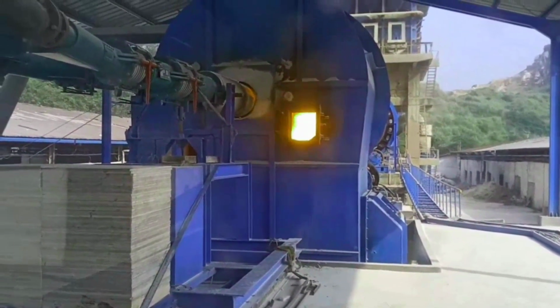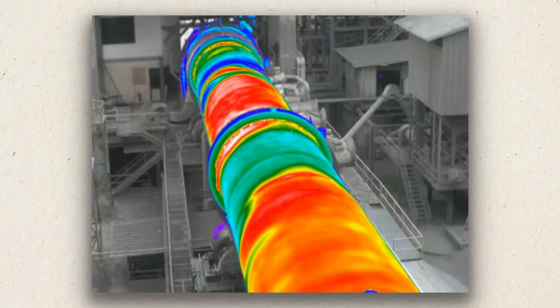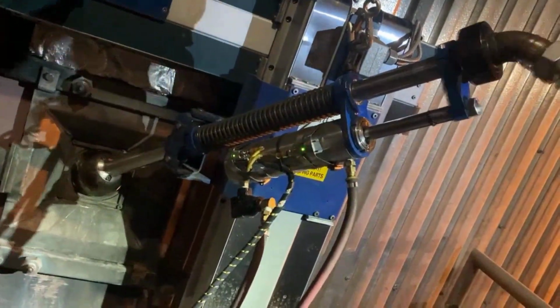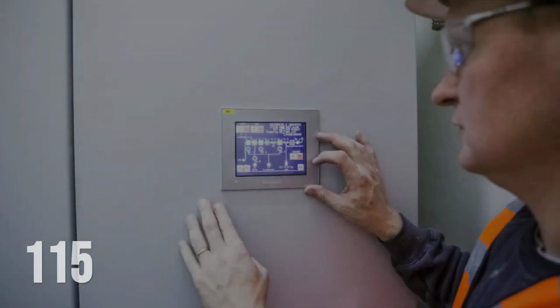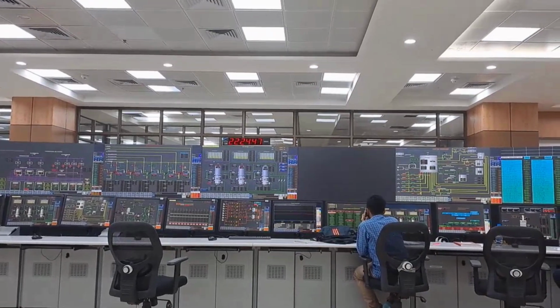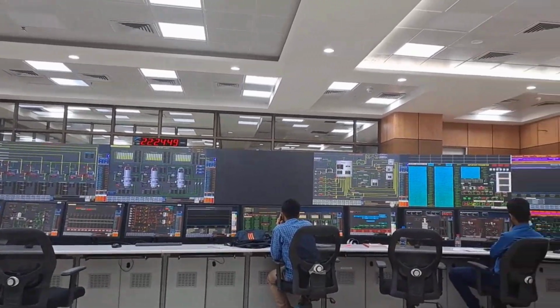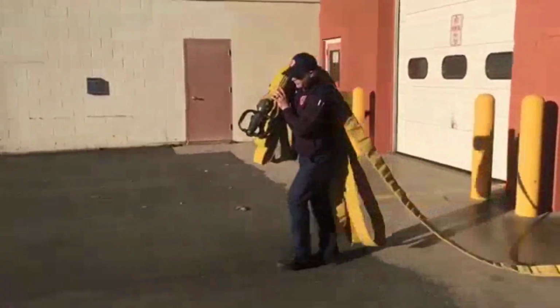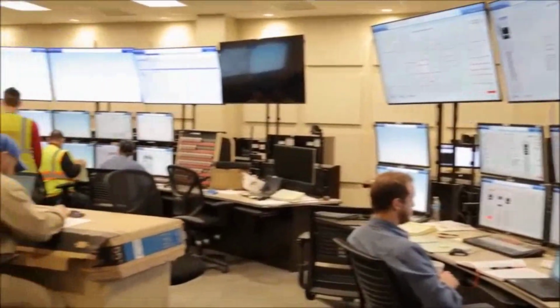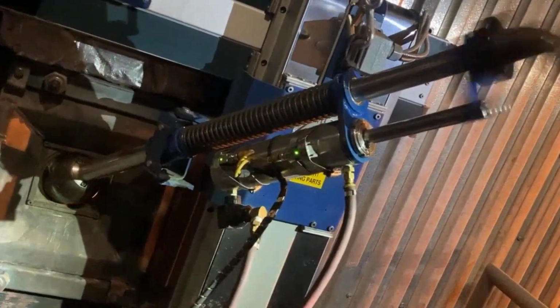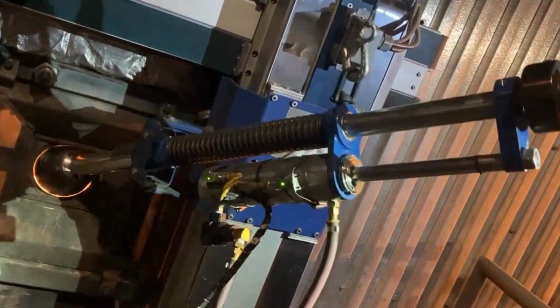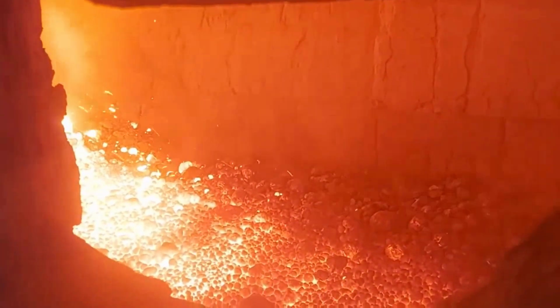Operators slowed the kiln, shifting the thermal gradient to weaken the deposit's grip. Carbon dioxide was injected directly at the snowman's base, quenching the surface and fracturing the crust. Real-time gas monitors tracked oxygen and carbon monoxide spikes, alerting the team to any risk of combustion instability. Within the hour, Luis Herrera's crew positioned a water cannon, guided by live camera feeds. The first burst cracked the shell, and the second sent fragments tumbling into the cooler.